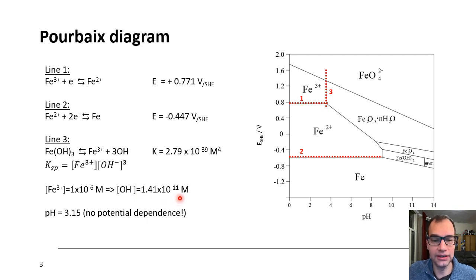Now, if you convert that to the pH, basically you can take the log of this and you get the pOH. Then you need to take 14 and deduct the pOH, and you get the pH, and that is then 3.15. And that is then how you come to this vertical line. There are no electrons involved, so this reaction does not depend on the potential.